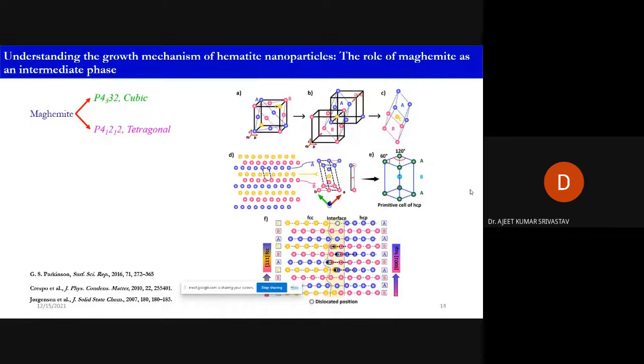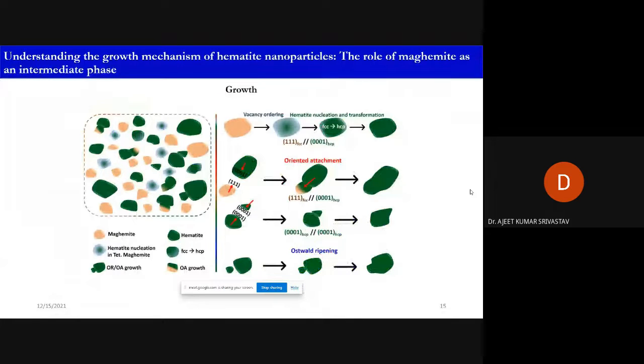Okay, so we have now the pathways, the transformation that happens from maghemite to hematite. As I mentioned, the vacancy site ordering leads to a c/a ratio of 3 for the tetragonal phase, and from tetragonal it finally transforms to hematite.